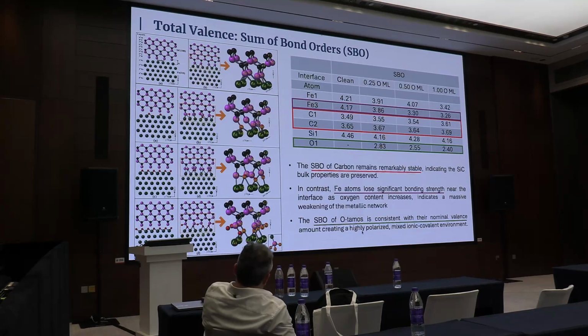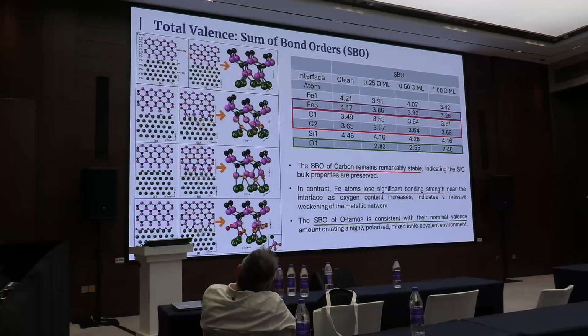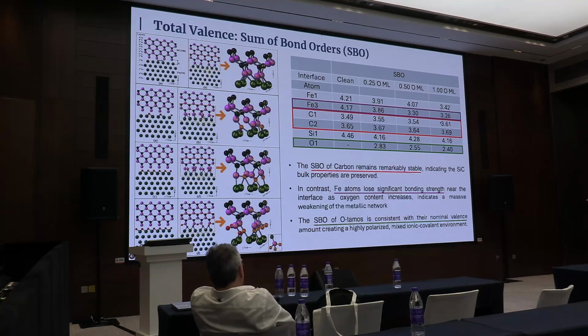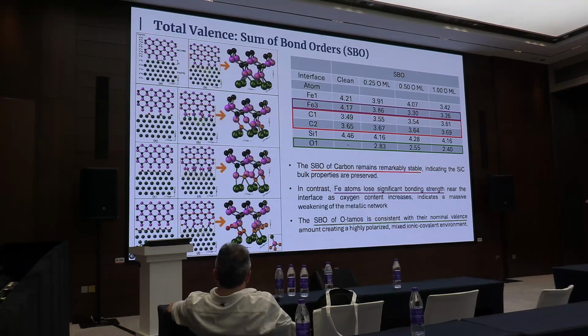In this case, we observe the same, but the thing that we observe here is that iron atoms are losing some electrons. So they lose electrons as oxygen appears. But the same for silicon. And if you observe the other part, the carbon atoms remain with the same bond order, so they are practically not losing or changing their connections. It's confirming more that our system is good to explain what is going to happen. And we observe that the oxygen is interacting too.